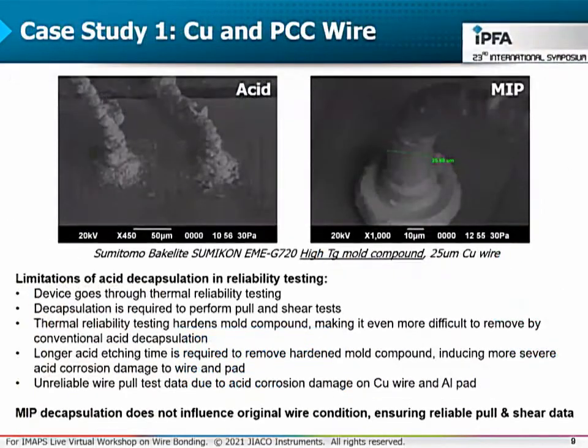Now, this slide shows a unique capability of MIP technology in the decapsulation of copper wire bonded IC packages after thermal reliability testing. After devices have undergone thermal testing, decapsulation is required in order to perform pull and shear tests. However, throughout thermal testing, the mold compound gets very hardened, and it is even more difficult to remove by acid. Removal of this mold compound requires a longer immersion time in acid, which causes more damage to the wire bond pads. Due to this damage, wire pull test data obtained after acid decapsulation will be unreliable.